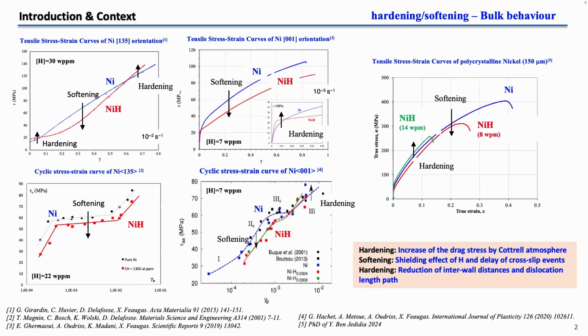And if you focus on the bulk crystal, in recent work, we show that when we add a different content of hydrogen, we have a softening or hardening, which is difficult to question. In terms of model, it's now well known that hardening is linked to the difficulty of the mobility of dislocations, because we have a drag stress imposed by the Cottrell atmosphere of hydrogen. The softening is linked to the shielding, a decrease of apparent elastic properties, and hardening is also, for large plastic strain, linked to the reduction of inter-wall spacing, which describes the cell structure.